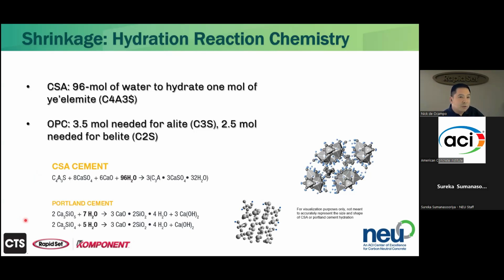For the 2 chemical equations for Portland cement, it's 3.5 moles needed for alite, 2.5 moles needed for belite. So it's 32 times more moles of water to hydrate a single CSA compound versus alite or belite, assuming roughly equal proportions. Again, this doesn't mean it requires 32 times as much volume of water - that would be ridiculous, that's obviously not the case. But as seen in the previous slide, a 0.45 water cement ratio is needed to hydrate all of the CSA and a good portion of the belite.